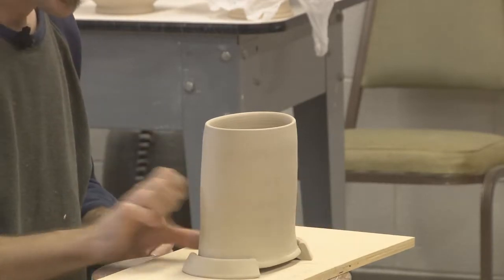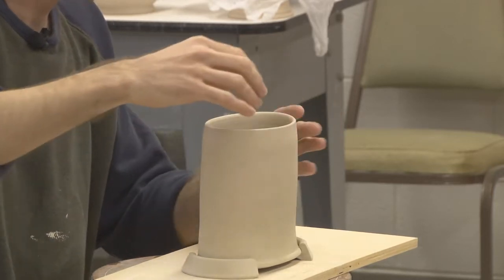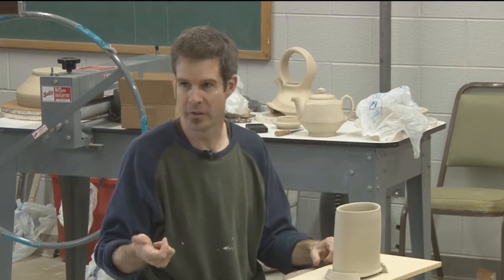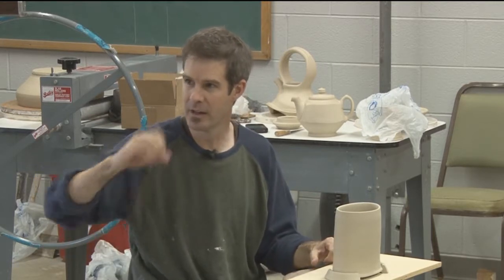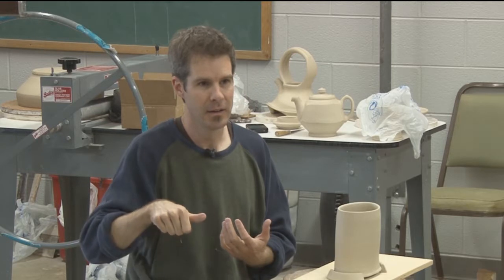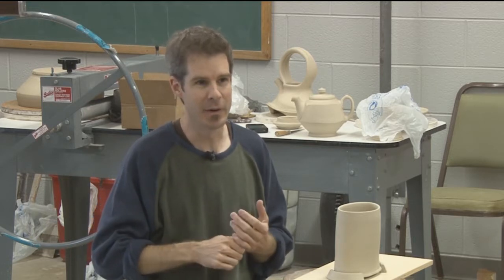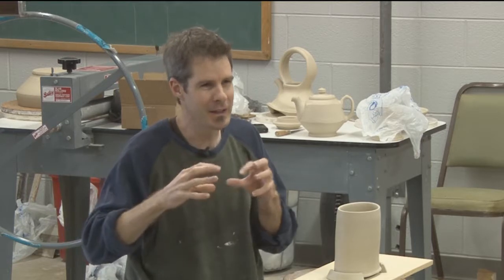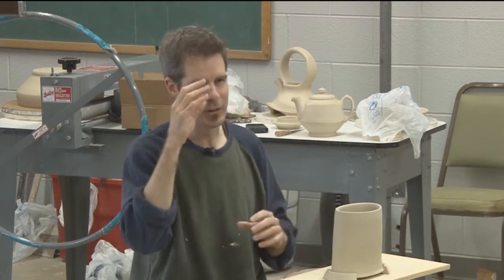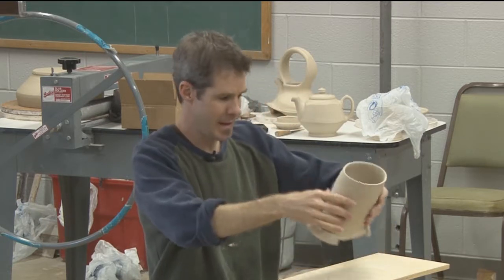I was having trouble with my bird beaks turning into balls, just balling up, and I couldn't figure out why. So I just started firing a little bit lower. The other thing I did was I got this kit that came with the compressor, and one of the things was this air spray. You compress this little lever and it sprays air out, like 40 pounds of pressure. So I'll go back to spots when I'm decorating and blow the glaze off areas that I don't want to be as heavy, like the faces of the birds. If the body shifts a little bit and the wing becomes a little bit bally, that's fine. But if it's the face or the eyeball, like I got a fox that looked like it had two eyes in a weird spot. So that's that piece finished.